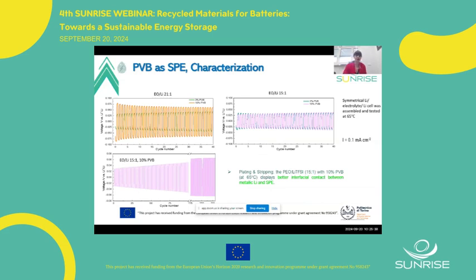Also, we made stripping-plating tests in the symmetric lithium cell at 65 degrees, and as we can see, again, the PEO-lithium 15:1 with 10% PVB showed the lowest overpotential value and also very stable behavior upon very long cycling.